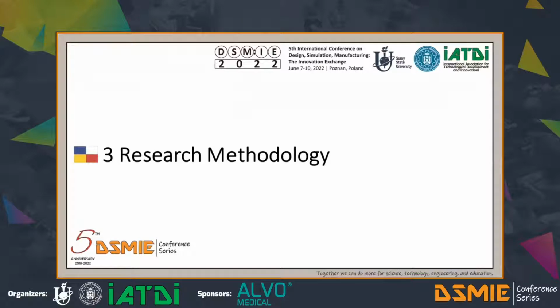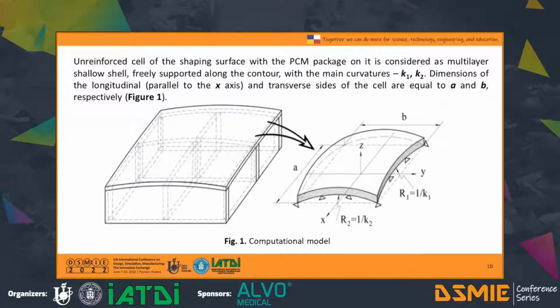The technological process of PKM product molding consists in giving it a non-reversible shape with the use of shape-generating molding tools throughout polymerization of the binder at a certain temperature and pressure, varying in time. When the temperature in the autoclave rises, the PKM package and shaping surface of the tool begin to deform. Due to the difference in their coefficients, PKM tends to move relative to the shaping surface. We assume that the friction force is sufficient to ensure that PKM does not slip relative to the shaping surface. To determine stresses, we consider the PKM plus shaping surface system as a layered shell under a temperature increase.